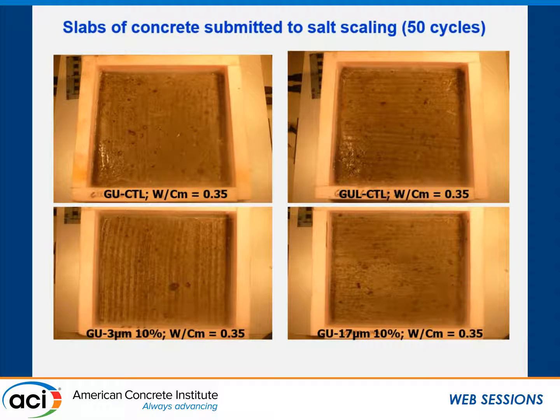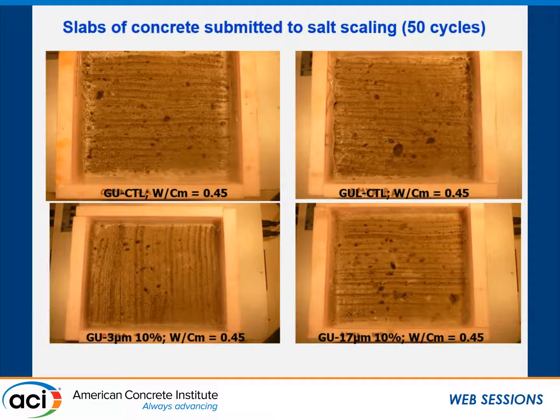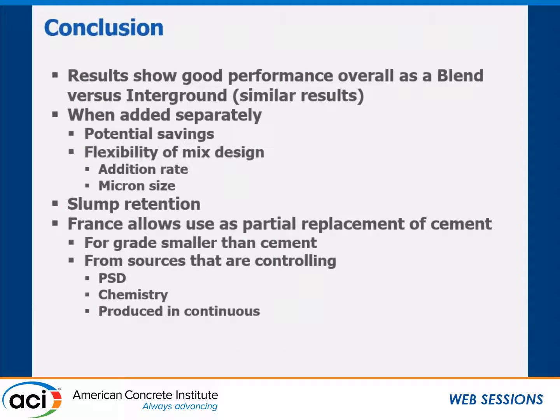For salt scaling resistance, I'll show only the 0.35 and 0.45 water-to-cement ratio mixes, because in Canada mixes exposed to salt scaling would never use a 0.70 ratio — the maximum allowed is 0.45. All mixes passed the test and looked good visually. At 0.45, the GU, GUL, and both limestone-addition products all showed acceptable results.